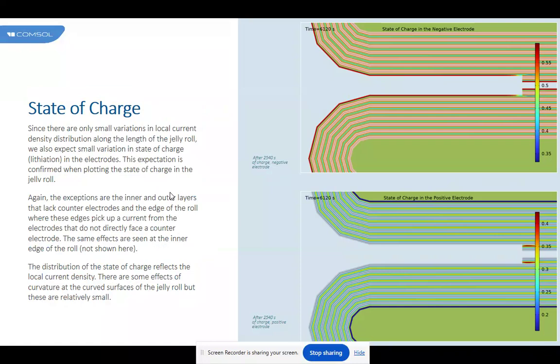State of charge. Since there are only small variations in local current density distribution along the length of the jelly roll, we also expect a small variation in the state of charge, the lithiation, in the electrodes. This expectation is confirmed when plotting the state of charge in the jelly roll.